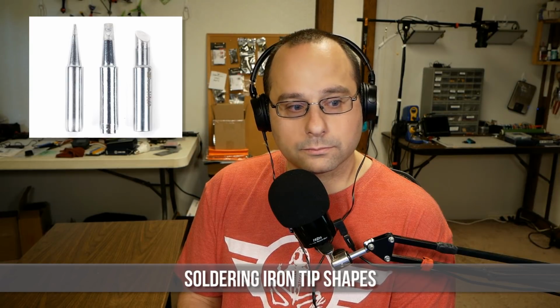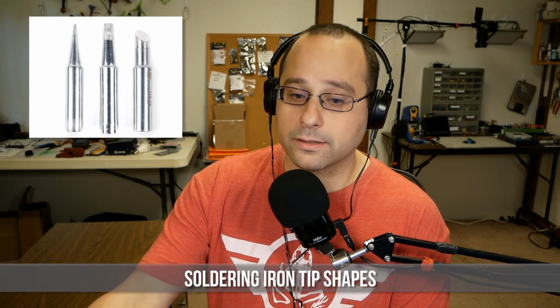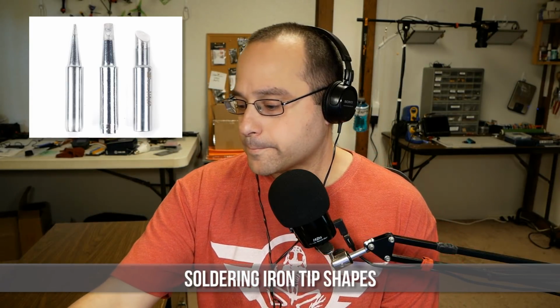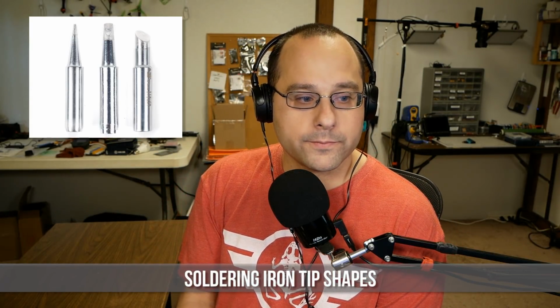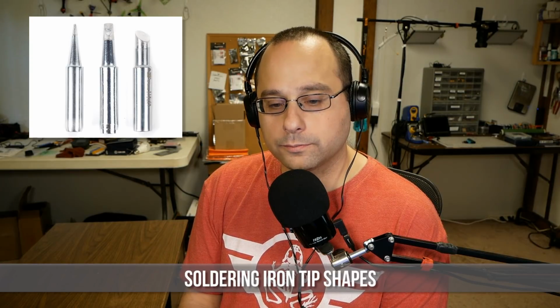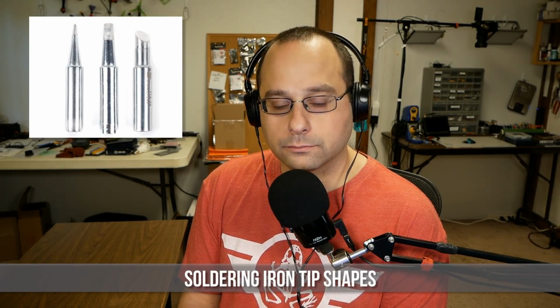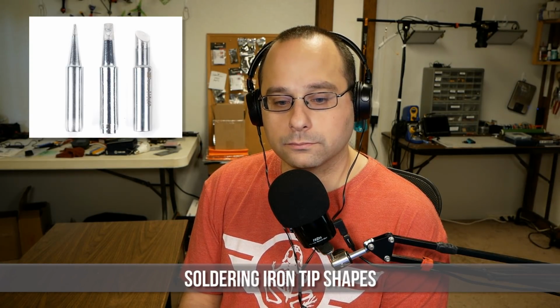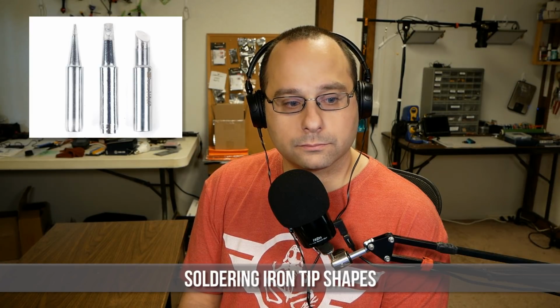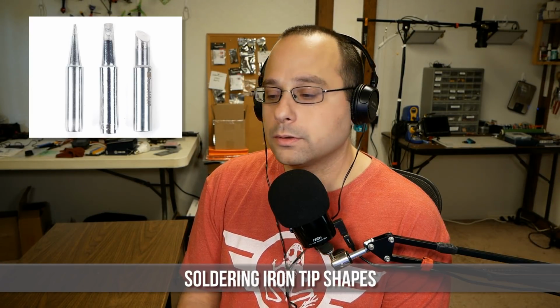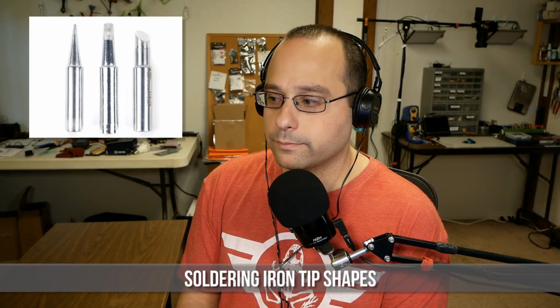Right. Okay, so let's talk about three major families of tips. There's a conical, which is probably what came with your iron, which is really a round tip, like a pencil on the end. Like a pencil, exactly. The next category is called a bevel, which has typically a 45 to 60 degree angle. So imagine taking your conical tip and cutting it at say a 45 degree angle. That's what a bevel tip looks like.